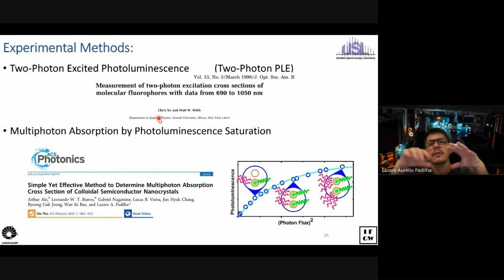And more than introducing uncertainties, the uncertainties are different for different samples. The question here is, what if we could come up with a way to reduce the relative error? When I say relative error, I mean if I measure 10 samples at the same time, the relative error among all these 10 samples could be reduced quite a lot. So we can do a volume comparison if we measure everybody together. So we came up with a simple model, a simple and very effective way to measure the multi-photon absorption cross-section of colloidal nanocrystals.